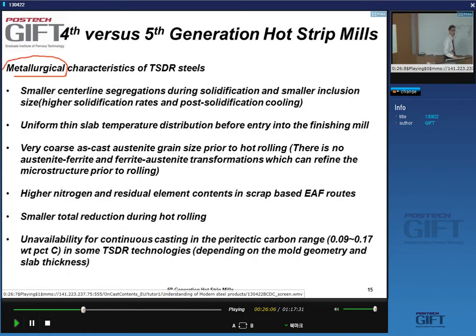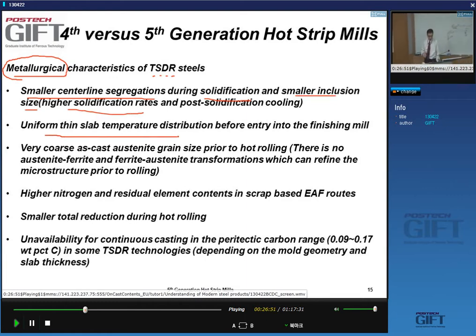However, we should never forget that we're making products and that the products need to have properties. In these thin strip direct rolling technologies, TSDR, we have smaller center line segregation during solidification and smaller inclusion size. That is because we have higher solidification rates, the slabs or the strips rather being thinner. A more uniform thin slab temperature distribution before entry into the finishing mill, that's right, certainly when you use a tunnel furnace. However, you do have very coarse as cast microstructures